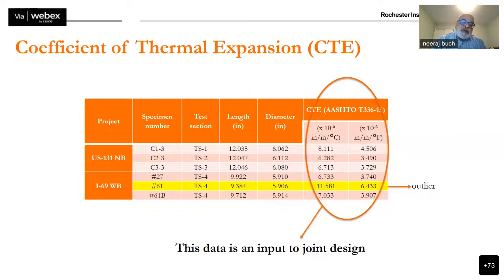And when you measure the coefficient of thermal expansion, the last two columns are showing you the linear coefficient of thermal expansion of concrete, both in inches per inches degree Celsius as well as degree Fahrenheit. So typically for limestones, especially the calcium carbonate limestones, the coefficient of thermal expansion is around 6 to 6.5 × 10⁻⁶ per degree Celsius. So other than one sample, which I have noted as an outlier, that could be a testing error, or it's hard to tell why that coefficient of thermal expansion was significantly higher than the others. But for the most part, the other coefficient of thermal expansions were within what you would expect from field cores.